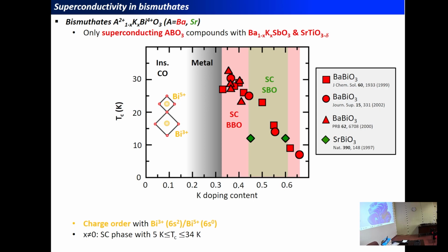And so I will focus on the bismuth-based compounds in which, through doping the material, we transit from an insulating state, which is associated with a charge density wave, from an unstable formal oxidation state of the bismuth cation, which should be 4+ in the material, but prefers to adopt the more stable 3+ and 5+ formal oxidation states in the ground state. And so it's producing an insulating state at no doping.